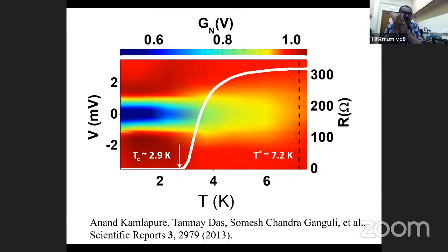Now niobium nitride is a superconductor that doesn't have any of the complications. It doesn't have any magnetic ground state, any additional complication that the high temperature superconductor has. So this was one of the early validations that indeed phase fluctuation can destroy superconductivity and produce a pseudogap state. However, you need a more direct proof, and for a more direct proof, you have to compare J and delta.